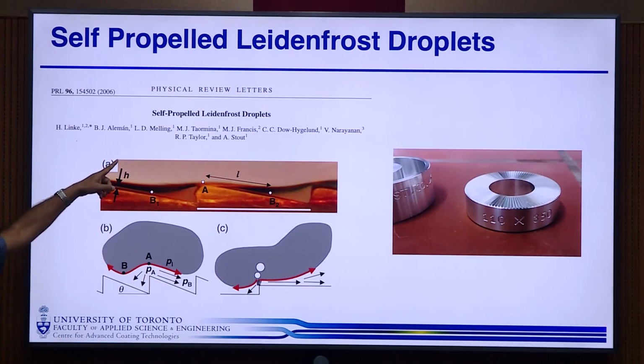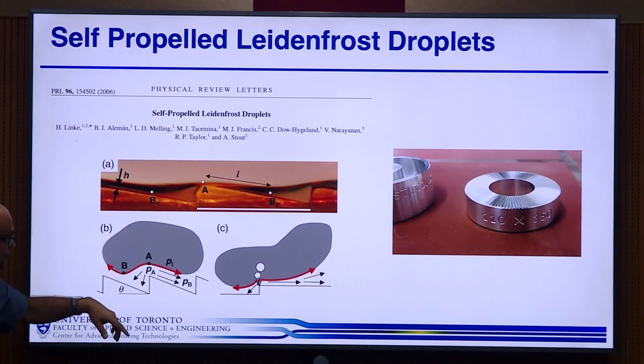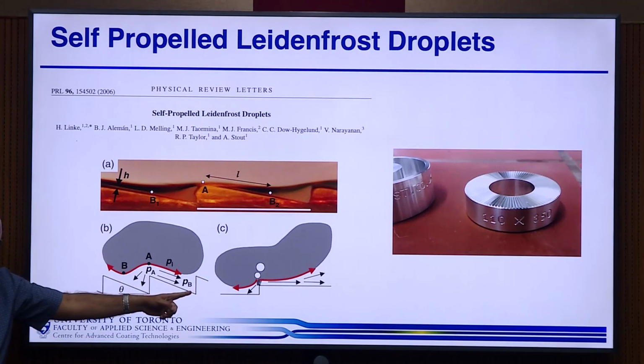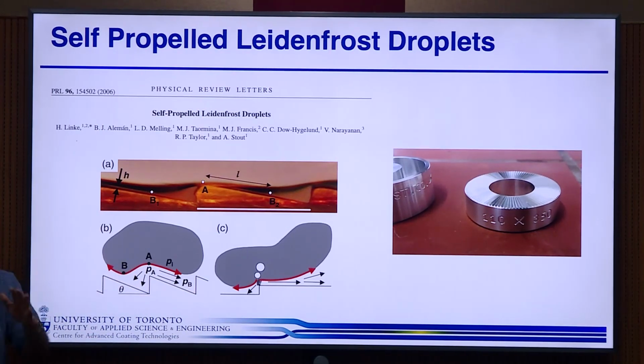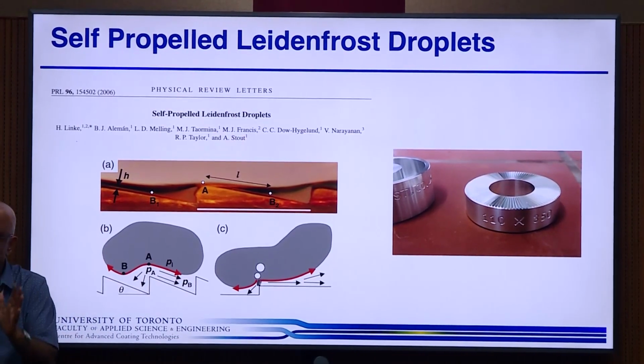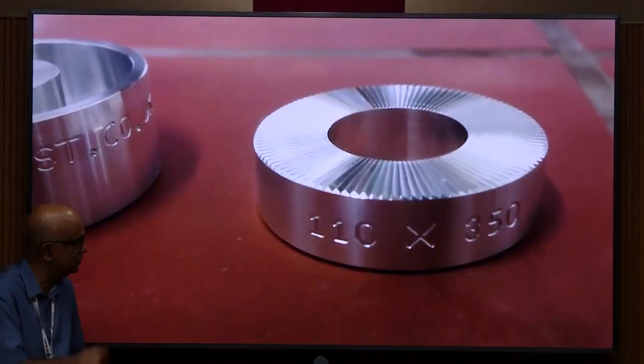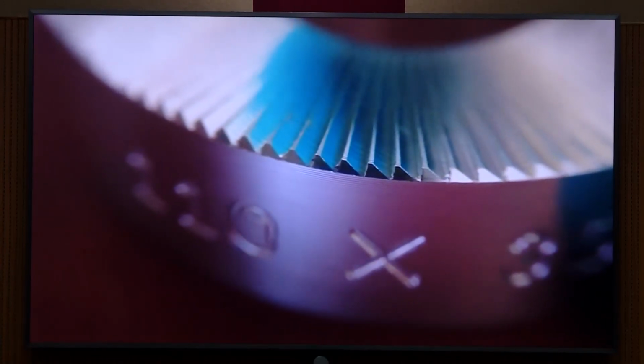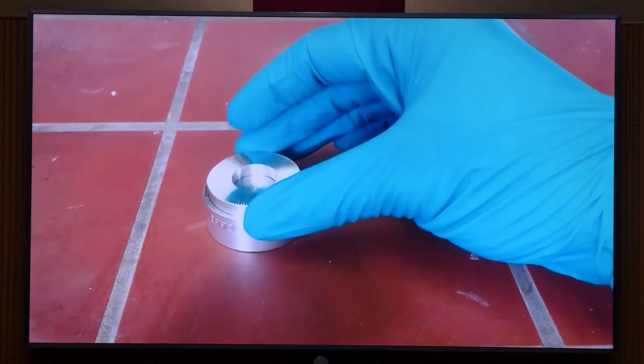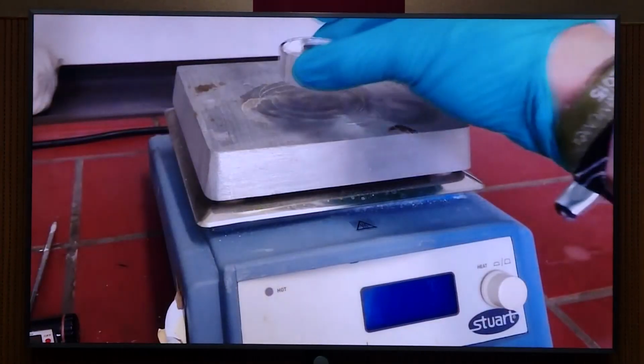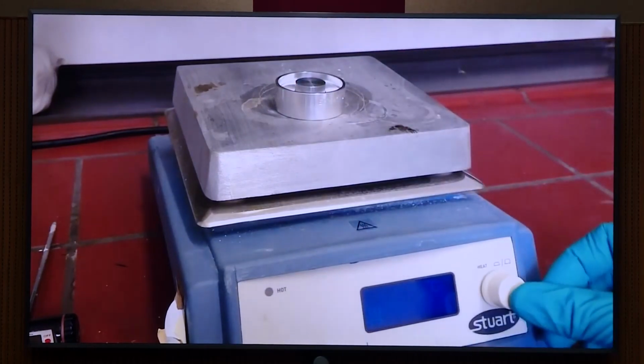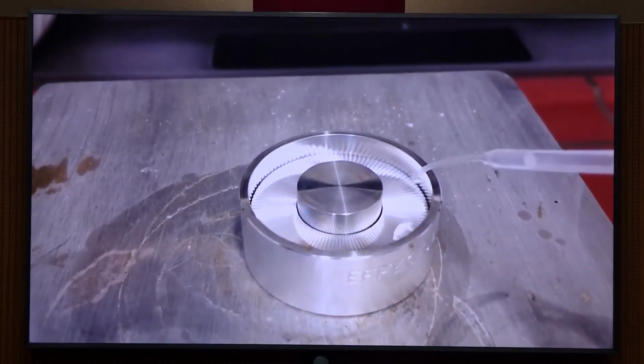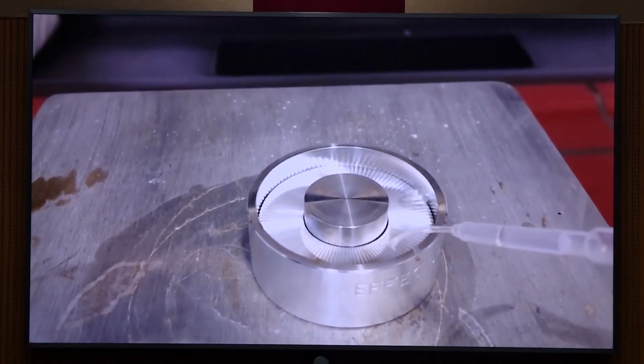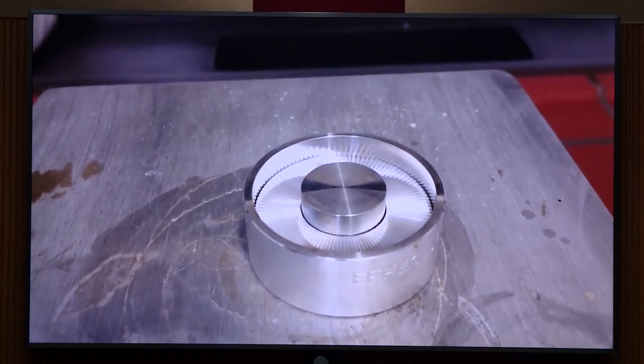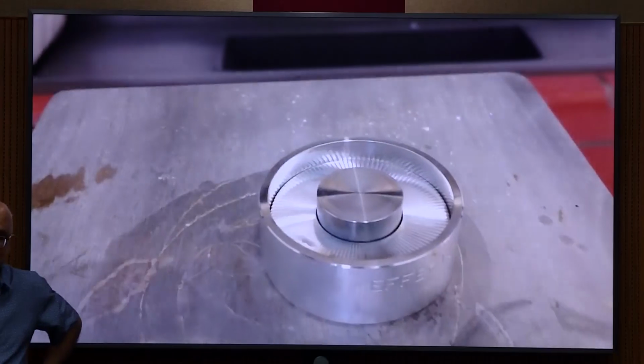So this was one particular paper years ago, self-propelled Leidenfrost droplets. The idea is if you put a Leidenfrost droplet on a surface and you have this sort of sawtooth structure, the forces acting at the bottom are asymmetric. So it will tend to drive it in one direction. And they had a very cute little video up on YouTube, so I thought I'd show that to people. So they make a ratcheted surface, they put it on a heater and heat this up, I think, to about 220 degrees C, and then you put a water droplet on that, and it'll keep running. It's self-propelled.